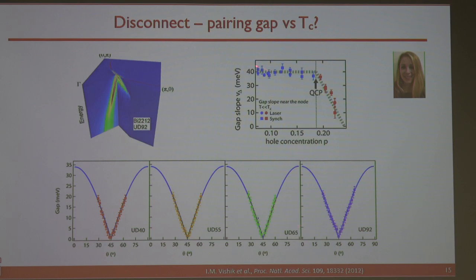Here in this work, what we find is that the node is best measured by the slope. And for those 4 samples with Tc from 40 Kelvin to 90 Kelvin, you see the slope essentially doesn't change in this range. Okay? Certainly, there's no factor of 2 change here. So this is telling you that the change of Tc from here to here is not related to the change of pairing. Of course, as you go to different parts of doping, then it becomes what you would have expected. As Tc goes down, the d-wave node gap goes down. Okay. So what is going on?